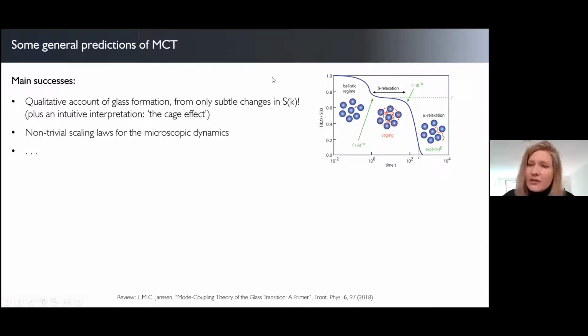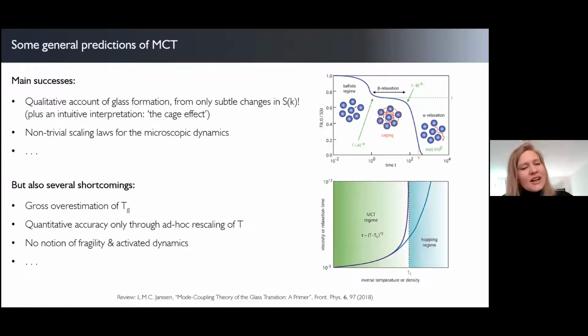However, the theory is obviously not exact. So there are also some things the theory cannot do so well. And just to mention a few, generally the theory always gets the temperature for the glass transition wrong. In fact, it always tends to overestimate the glassiness of a material. And that also means that the theory is never really quantitatively accurate at any temperature, really.